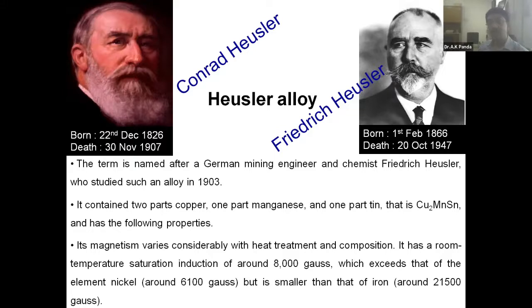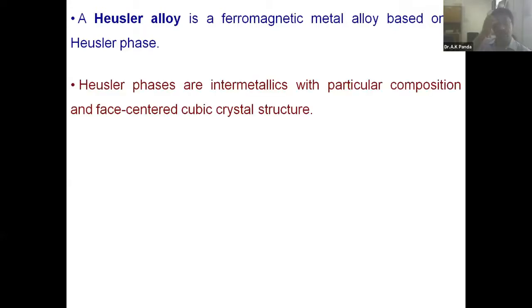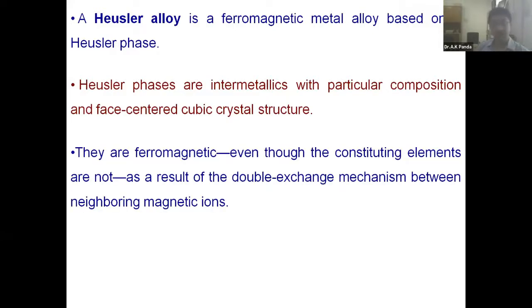it was a fantastic observation because none of them are magnetic, ferromagnetic rather. So, in spite of that, the exchange coupling and all those things, and these are basically the intermetallics and the line compounds, and they revealed very good potential magnetic properties, much better even than nickel. So later on, the Heusler alloys stepped in. Basically, these are intermetallics. They are face-centered cubic. They are ferromagnetic, and there is, of course, a double exchange mechanism between the neighboring atoms.